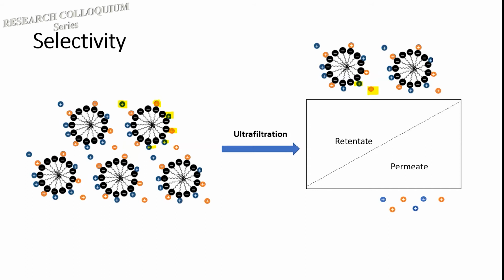So here we read a few articles. They talk about the influence of micelle formation together with the presence of metal cations. Based on their reports, they found that different types of metal will have a different impact on the formation of the micelle. This is significant especially when the concentration of the SDS is very, very low. So it gives us a very good idea: what if we limit the amount of SDS? We reduce the concentration of the SDS so that both of the heavy metal cations fight to adsorb onto the SDS micelle. This is what we call competitive adsorption. We try to utilize this competitive adsorption to see whether we can achieve selective separation in this MEUF process.